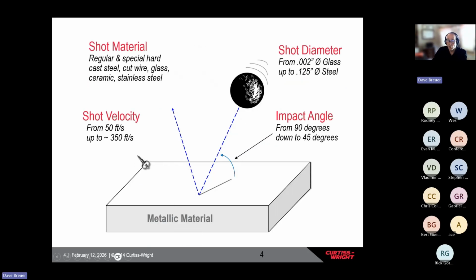So being a shot peening job shop, we stock a lot of different media for different situations. We have different hardnesses of steel shot, peening grade glass beads, ceramic and stainless steel, and a pretty wide variety of shot sizes—from the smallest at about a 2/1000 diameter glass bead up to an 1/8 inch BB. Depending on the application material, that helps dictate the shot material, and the geometry needing peening dictates the size of the media.